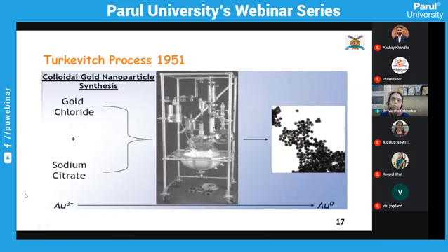So I showed you the gold sol that was prepared by Michael Faraday, wherein he had used essentially phosphorus in carbon disulfide as a reducing agent. But the first scientific report in the form of a publication for the gold nanoparticle cites the Turkevich process, the famous Turkevich process, which was reported in 1951 for the colloidal gold nanoparticle synthesis, and which reported the use of sodium citrate, where the gold salt or the gold chloride was reduced using a chemical reducing agent such as sodium citrate, using a simple reactor that can be used for any other synthesis purpose.